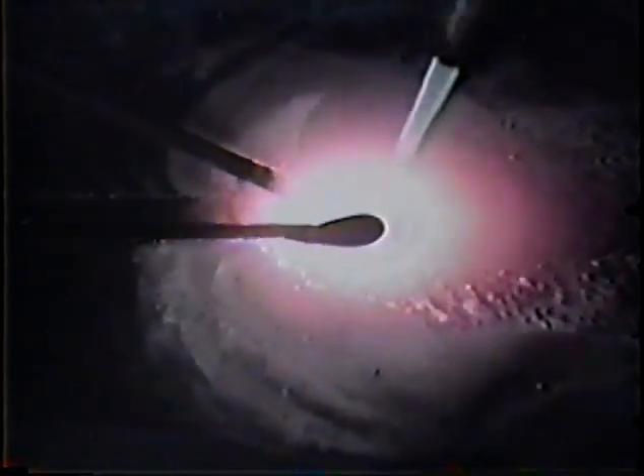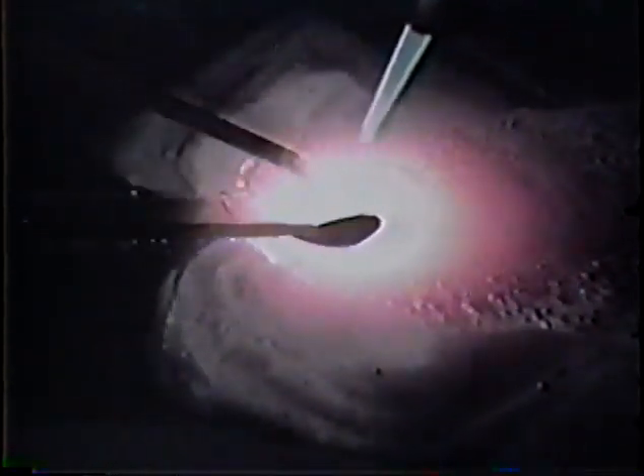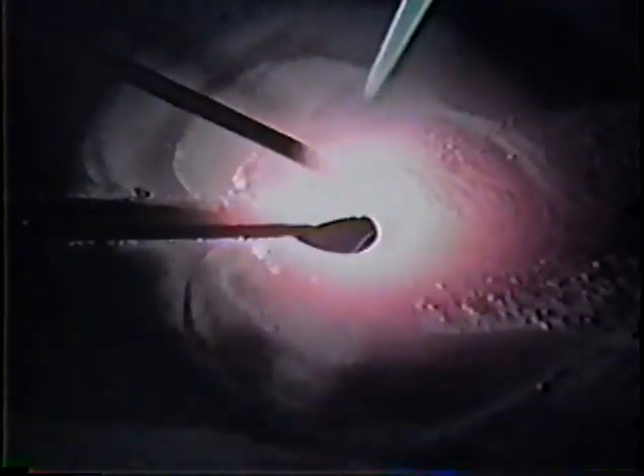If too much rod is used, the keyhole appearance will disappear and you'll wind up with a straight kerf. The back of the weld will show straight edges and a lack of penetration. If too little rod is used, the joint will not fill up and thin areas or holes will result.